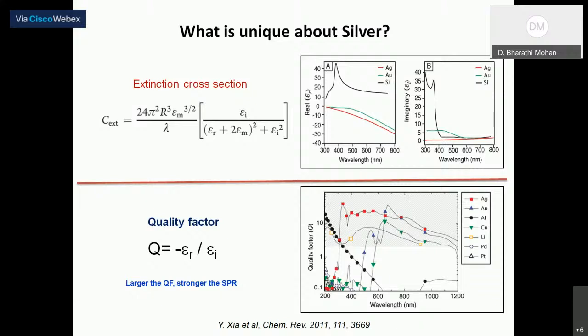Coming to the quality factor, which describes the strength of the surface plasmon resonance. The equation is: Q is equal to the negative of the real part of the dielectric function divided by the imaginary part of the dielectric function. The larger the quality factor, the stronger the surface plasmon resonance. The quality factor must be greater than 10 for any good plasmonic material. And if you look at the graph on the right-hand side, the quality factor is greater than 10 all through the region from UV to near IR for silver metal.